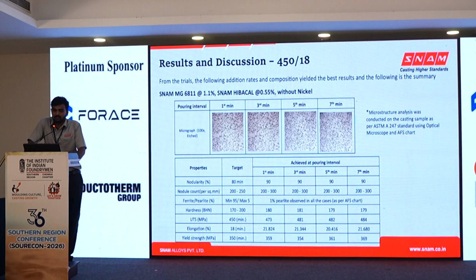When we try to produce 450/18, this is the best combination. With 1.1% of magnesium and inoculant of 0.55%, we have achieved the mechanical properties and metallurgical properties as per the 450/18 grade. These are the mechanical and metallurgical properties at different pouring time intervals.